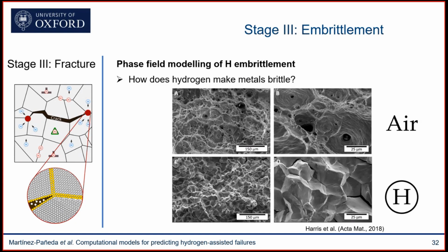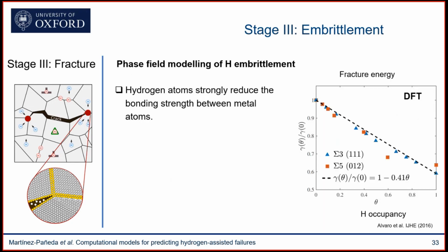How can it possibly be that a material like this one that fails in a very ductile fashion through microvoid cracking mechanisms in the absence of hydrogen suddenly fails in a very brittle fashion, with cracks often propagating along grain boundaries in the presence of hydrogen? And in my opinion, to understand why this happens, how just by adding hydrogen into the material we see this ductile to brittle shift, we need to understand three key ingredients.